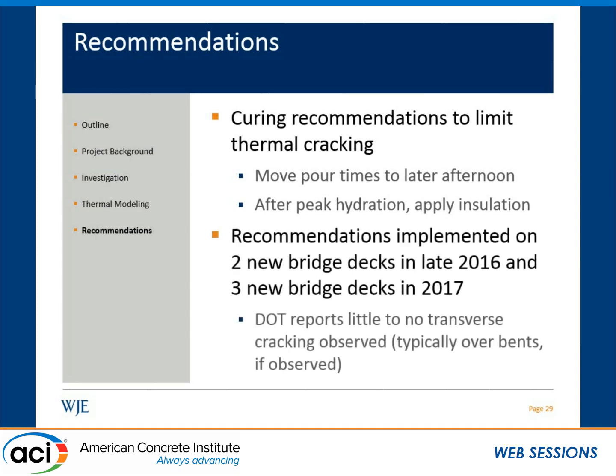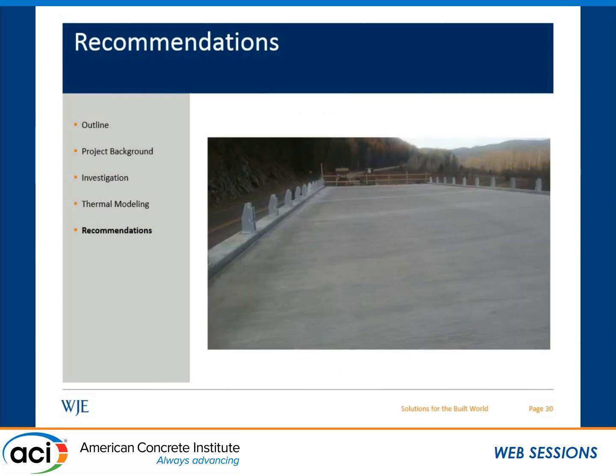recommendations on 2 bridge decks in late 2016 and on 3 new bridge decks in 2017. And they've reported to us that they've seen little to no transverse cracking. Typically, if they do observe cracks, they're usually over the bents or piers where the restraint is much higher. They sent us this photo of one of the bridges shortly after they removed all of the formwork. And this is the insulation and curing. This is typically when they would go out and seal all the cracks, and they sent us this photo to say we didn't have to seal any cracks.